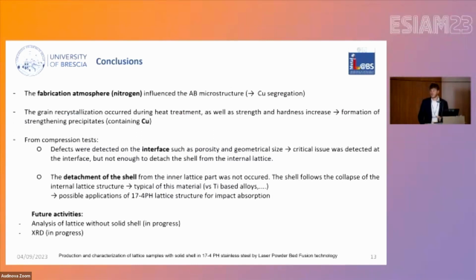At the end of this work, I concluded with some considerations. The fabrication atmosphere of nitrogen, as I said before, is a good austenite stabilizer, and so it influences the microstructure of the as-built sample, generating the copper segregation rich in copper, as I said before. The grain recrystallization occurred during the heat treatment, as well as strength and hardness increase, and the formation of strengthening precipitates containing copper. And from the compression test, defects were detected at the interface, such as porosity and geometrical size deviations, in particular at the node and close to the connection between the two different dense parts.